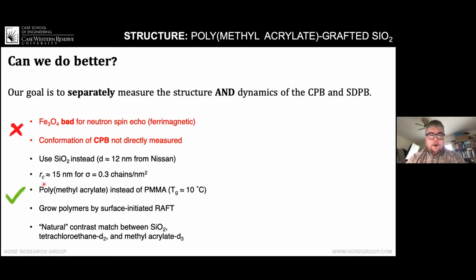We can predict that RC for this particular system is about 15 nanometers. We used a different polymer. The previous example was polymethyl methacrylate. We're going to use polymethyl acrylate instead because its glass transition temperature is 10 degrees. And if we want to measure the dynamics, we'd like to get well above the glass transition temperature.